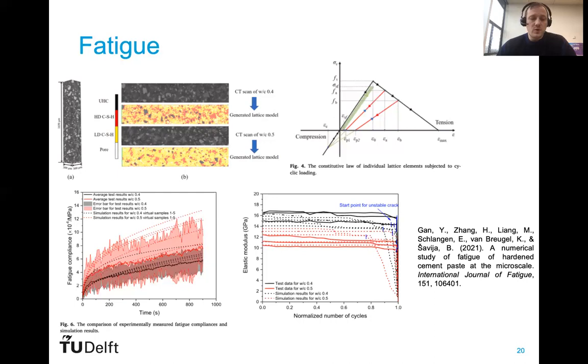But with this approach, we're also able to simulate the fatigue compliance for different water cement ratios in our micro cantilevers. And also what we have seen is that actually at the level of cement paste, the damage is very minor. So very little change in the elastic modulus for a very, very long time, in a lot of cycles. And then there is a sudden loss of elastic modulus and sudden damage. So this is something that we found was also very interesting experimentally, but we were also able to numerically explain how and why this happens. So these models that I show here were physical models.